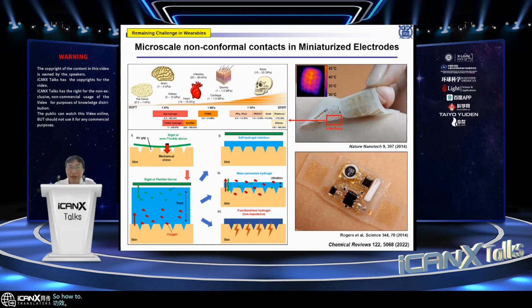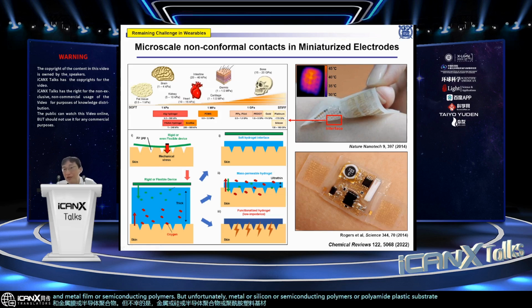So how to solve that issue, how to remove these air gaps? The solution is to incorporate softer materials. Actually, flexible devices are typically made of plastic substrate and metal film or polymer, semiconducting polymers. But unfortunately, metal or silicon or semiconducting polymers or polyimide plastic substrate have the modulus of gigapascal range, which is much higher than the tissue modulus.